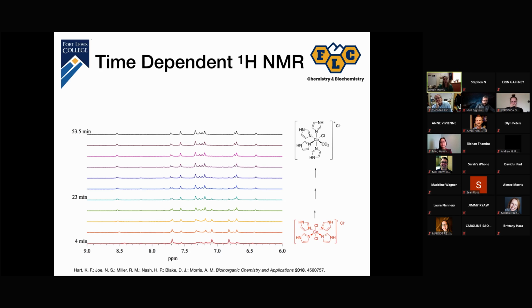So this is very, very labile in the presence of water. There's definitely substitution reactions that are happening very quickly on a minutes time scale. And so we kept that NMR tube in there and we monitored what was happening to the NMR spectrum over time. And the other thing that's really cool is that we actually see a visible color change again. The NMR tube starts out green and it goes to a red color by the time we're done with this particular timing of the reaction.